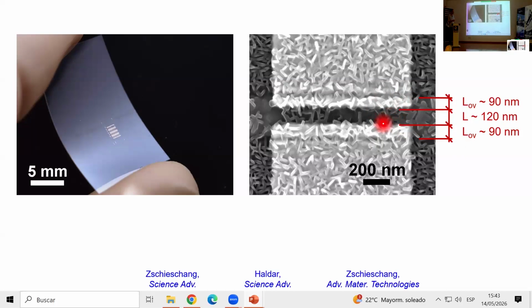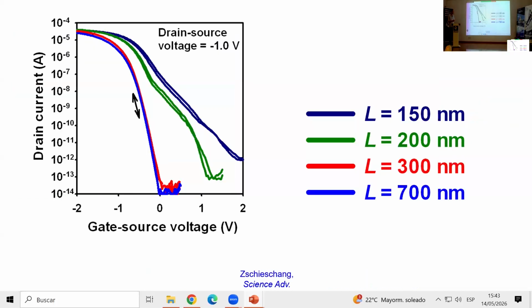So gate channel length 100 nanometers and overlap on the order of 100 nanometers. And these are the measured transfer curves of diphenyl DNTT transistors with channel lengths of 150, 200, 300, 700 nanometers here, and overlap of 100 nanometers. And you see the on-off current ratio here is on the order of 8 orders of magnitude or so. And the off-state drain current here for the transistors with channel lengths of 300, 700 nanometers is in fact at the noise limit of 10 femtoamps. So it couldn't be any smaller at this point, right?